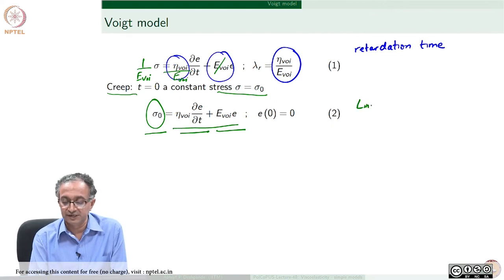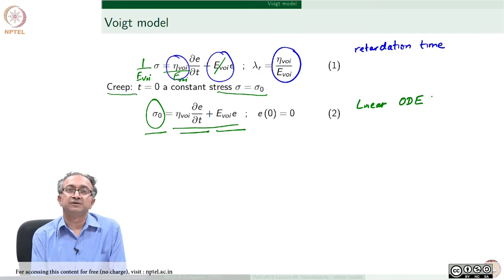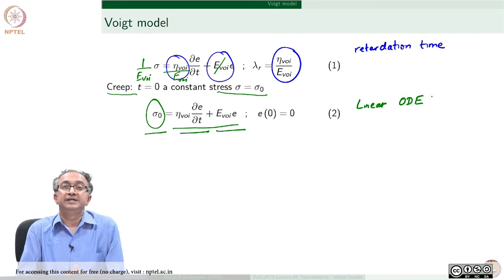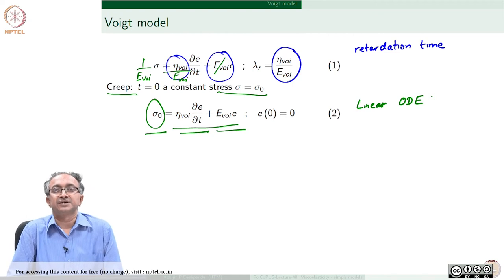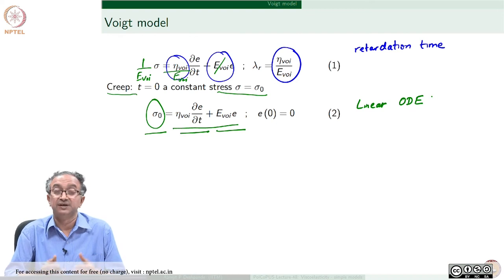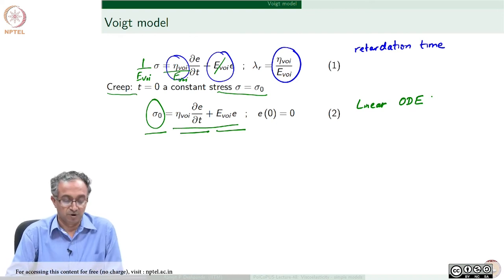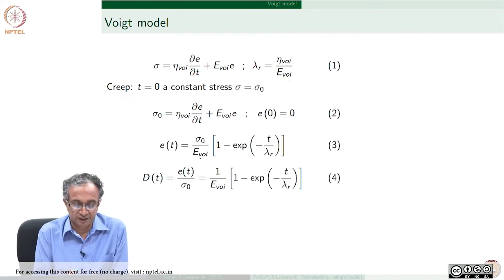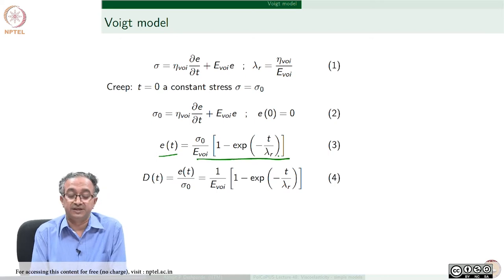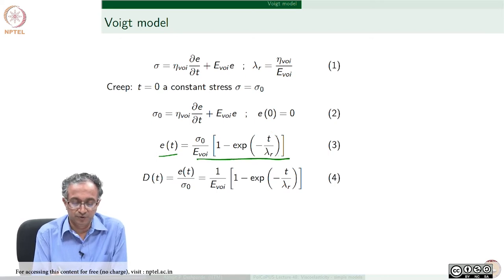Note that this is a linear ODE — we have discussed how the governing equation for linear viscoelastic or linear dielectric response will be a linear equation. The Voigt model is therefore an example of a linear viscoelastic model. The solution for strain is just an exponential increase: when time is 0, strain is also 0, and when time is infinity, the strain becomes constant.